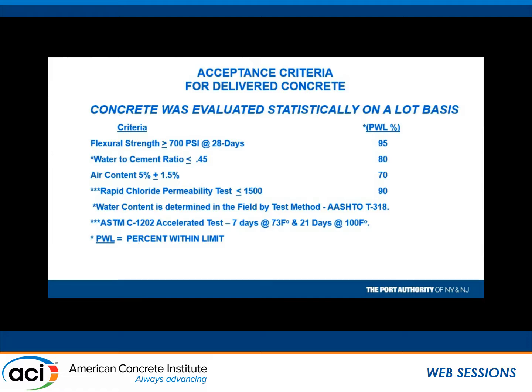And again, to have pavements with low permeability, that's not a bad deal. It's not as important as for a bridge deck, okay? But we wanted to make sure that the pozzolan got in there. It gives you protection in the event that maybe you got some aggregate in there that's reactive. If you have 40% slag, 30% fly ash in there, it's not going to be as reactive, and you're not going to get runways that blow apart in 7 or 8 years, as some of us have heard is happening in other parts of the country.